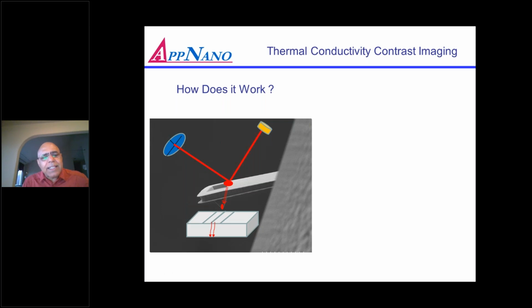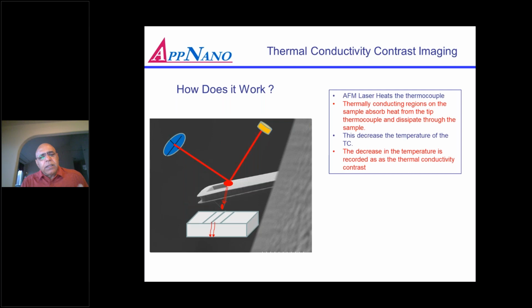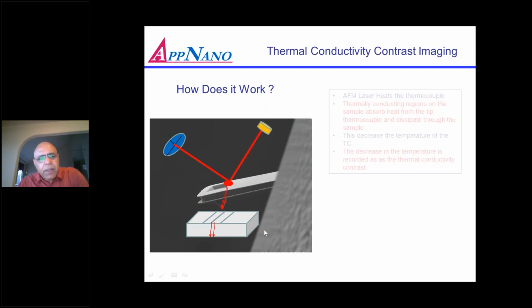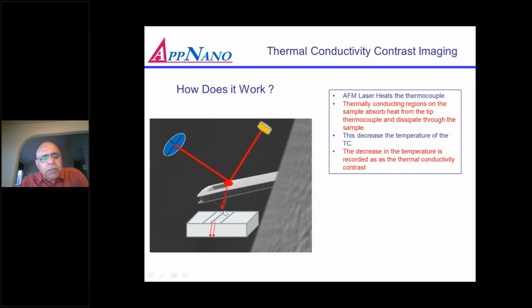The way it works is once you increase the temperature above the room temperature, the thermocouple, now this nanorod, is above the sample temperature. So when you're scanning the probe on areas of different thermal conductivities, if the thermal conductivity is higher here, it will take the heat from the thermocouple, and the temperature will go down. This change in temperature is recorded as a thermal conductivity contrast. So when you are in an area where there is no thermal conductivity change, the temperature will stay where it was originally, and when the thermal conductivity is higher, the temperature drop will be higher. So this is how you can record the change in the thermal conductivity contrast through the change in the temperature.